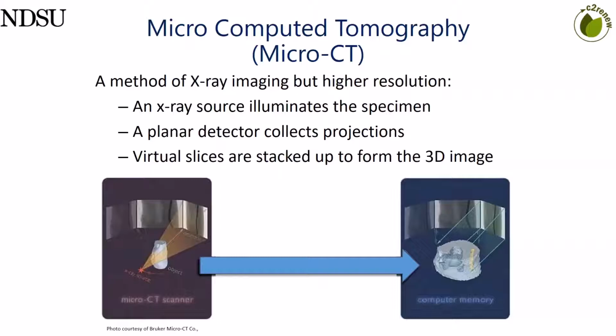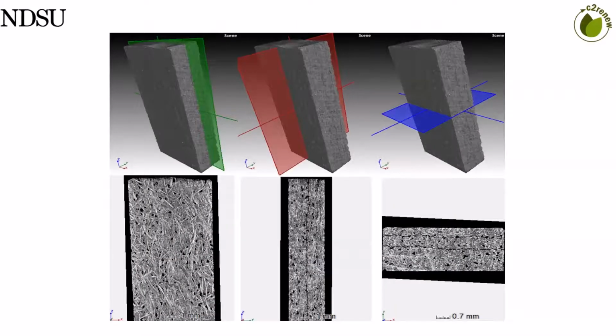So we've turned to instrument micro CT, where we're able to X-ray the structure, and we've seen some pretty decent results where we can assess voids, fiber orientation, and fiber volume fraction. This particular specimen was tested in flexure, and we saw how some shear failure occurred through the thickness of the composite. We can do a nice assessment of the material without degrading it, say through thermal or chemical means. We can assess the inside of that composite relatively easily with micro CT.